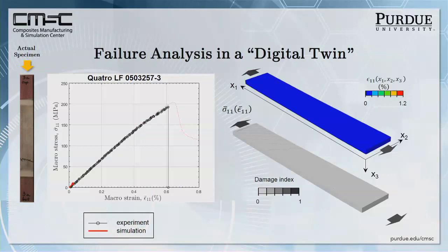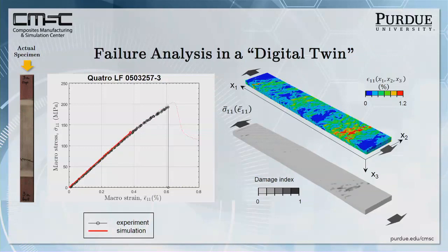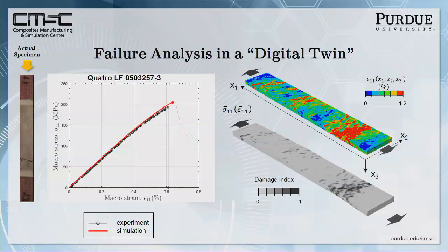That's true. So here's a typical prediction. Not the best, obviously. I wouldn't be showing it to you, but this is our experimental prediction on the right. You see the virtual sample, and you can see the intensity of deformation and damage here. And as this is the sample here showing damage. And if you look over here at the real sample, not only did it fail almost exactly in the same spot, but it failed along the same failure path.